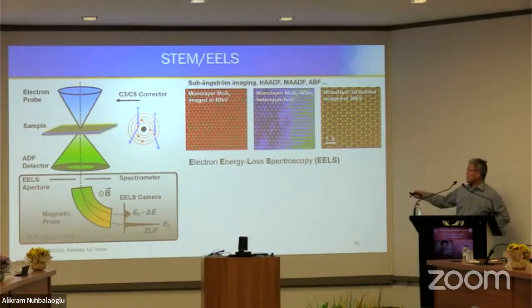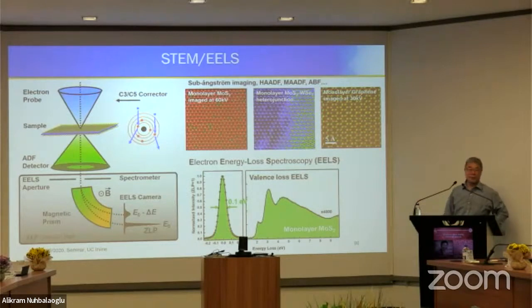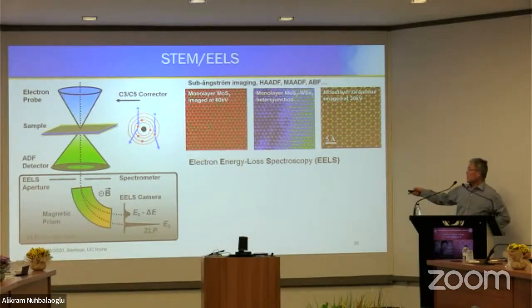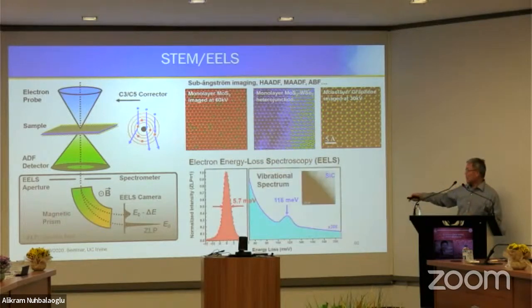The electron can be scattered by valence electrons, and then this will allow you to study the electronic property like a bandgap and anything related to the valence electrons. Or electrons scattered by nuclei, and then nuclei vibration, that is like a vibration of lattice or phonon. This involves very small energy change in the electron beam, but now with a new technique developed, a very small change, like a few milli-electron volts, can be detected. Traditional TEM can only detect energy change of 100 milli-electron volts or higher. These are monochromated TEM.